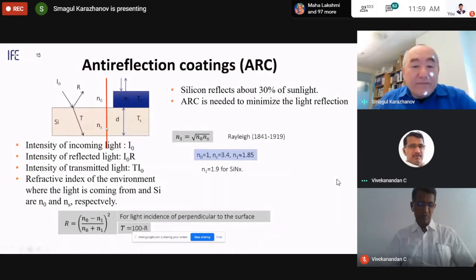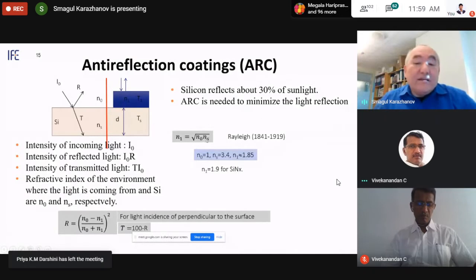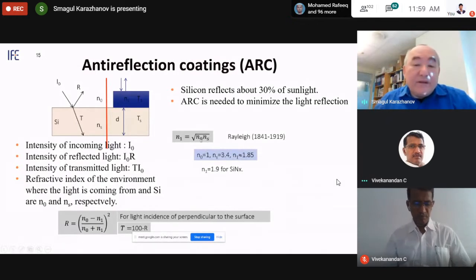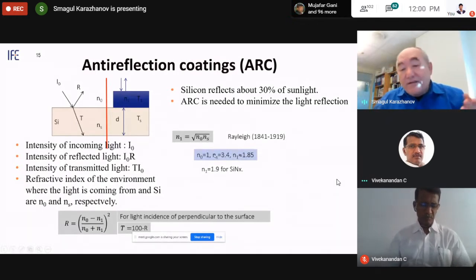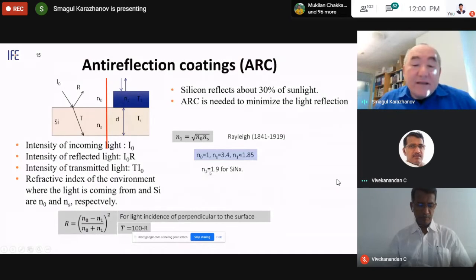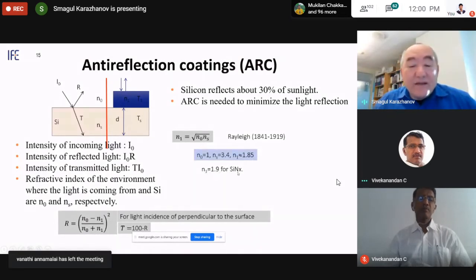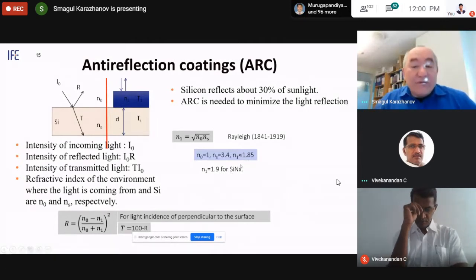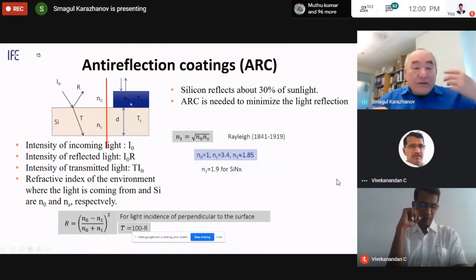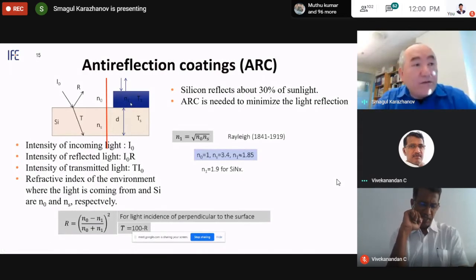To minimize light reflection, the refractive index of the antireflection coating should be the square root of the product of the refractive indices of the environment, for example air, and the semiconductor, silicon. Silicon refractive index is about 3.4. If the refractive index of air is 1, then the square root would be 1.85, whereas it is 1.9 for silicon nitride. So silicon nitride best suits both as an anti-reflection coating and also as a surface passivation layer.